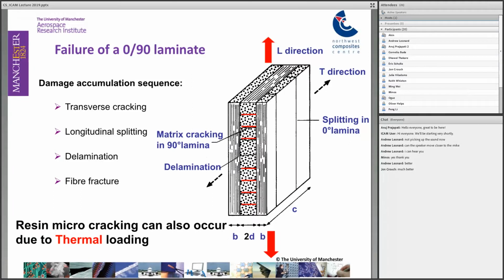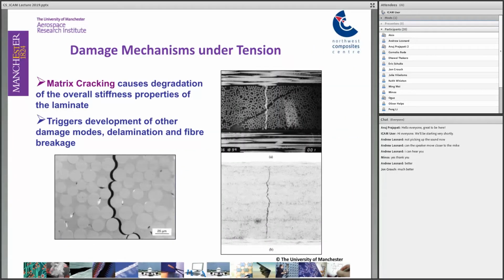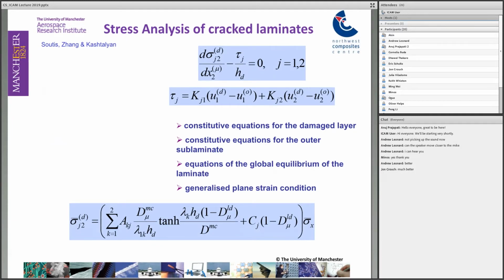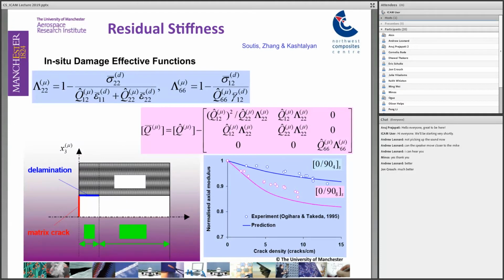And this type of resin microcracking can also occur not only due to static loading or fatigue loading, but also due to thermal loading, or a combination of thermomechanical loading, something that an aircraft experiences when in service. So the damage mechanisms under tension are in the form of matrix cracking that causes degradation of the overall stiffness properties of the laminate. And that triggers development of other damage modes, delaminations and fiber breakage. And our community then puts an effort to develop analytical models that can describe the effect of all these damage mechanisms on the performance of the composite structure.